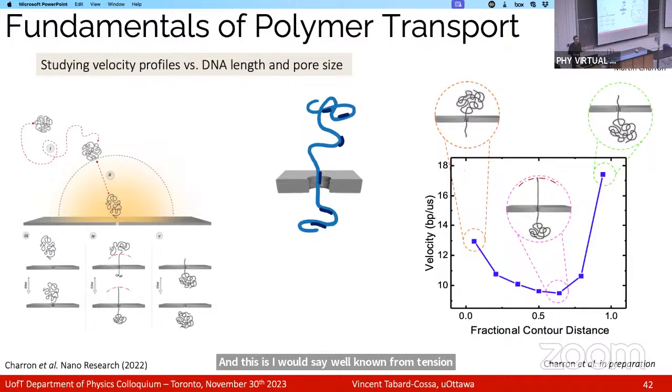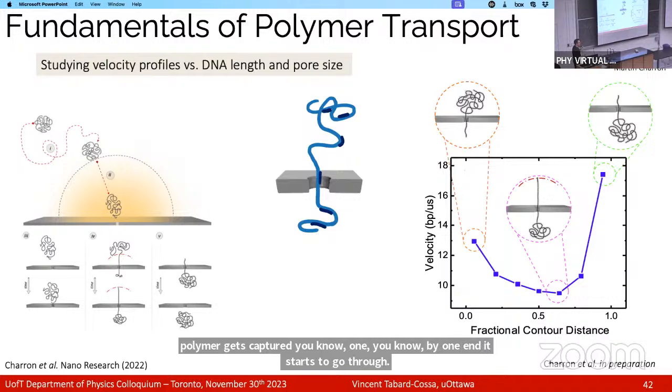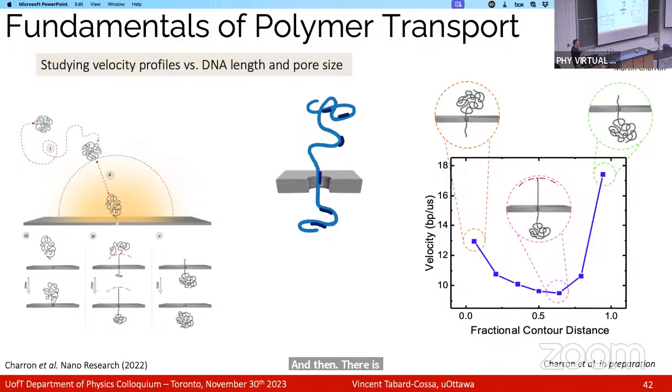And at the molecular level, tension propagation theory essentially says that when the polymer gets captured by one end, it starts to go through, and this is a non-equilibrium process, and so there's tension that propagates through the chain, and so more segments of the DNA are set into motion, and this increases the friction essentially. As more polymer is moving, you have more friction, and this explains the slowing down of this polymer. Up until the tension front reaches the end of the polymer, where the friction term starts to reduce, and then you get acceleration towards the end,